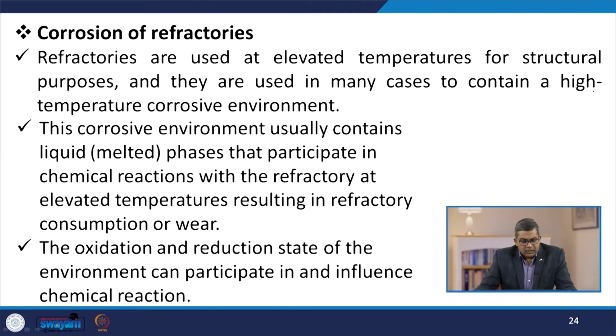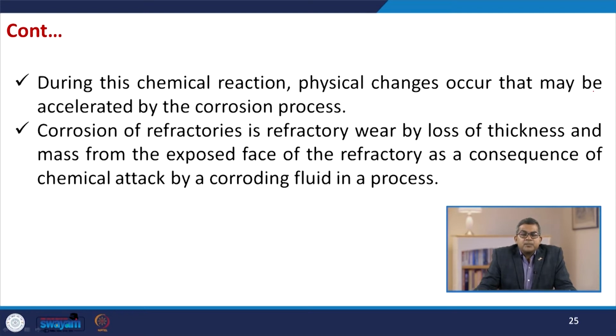Now let's talk about the corrosion of refractories. Refractories are used at elevated temperatures for structural purposes, and they are used in many cases to contain a high temperature corrosive environment. This corrosive environment usually contains liquid, that is in the melted phase, and that participates in chemical reaction with the refractory at elevated temperatures, resulting in refractory consumption or wear. The oxidation and reduction state of the environment can participate in and influence chemical reaction. During this particular chemical reaction, physical changes occur that may be accelerated by the corrosion process.